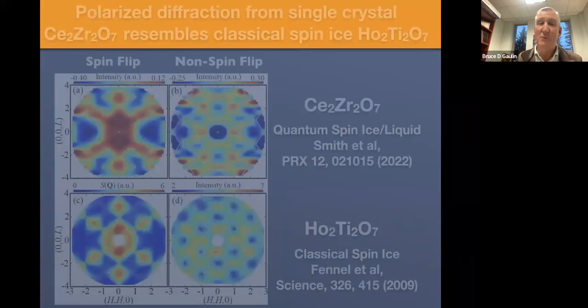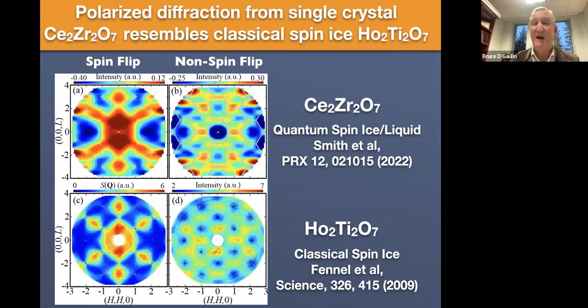Okay, and we can do a more sophisticated version of that same experiment. We could look at the Q dependence of this diffuse scattering, but we can do it with polarization analysis. And that's what we did using the D7 diffractometer at the Institut Laue-Langevin, Grenoble. Then we can also measure this pattern of diffuse scattering, but now we can explicitly measure it only for those neutrons that have been diffracted with a flip in their spin, and we can separately look at the cross section for those neutrons which were diffracted without a spin flip. And this is an interesting thing to do for a couple of reasons.